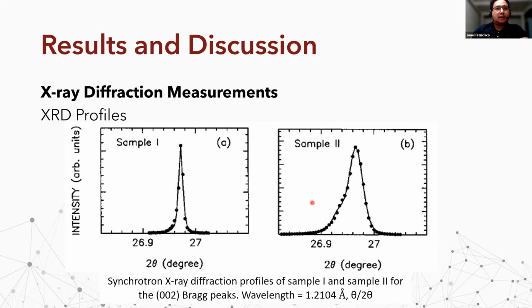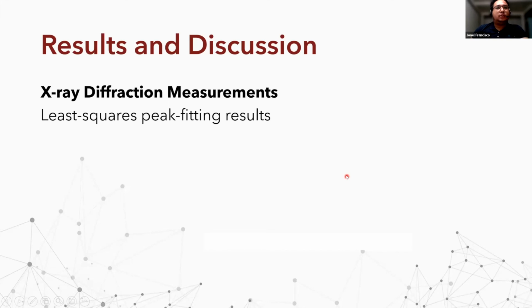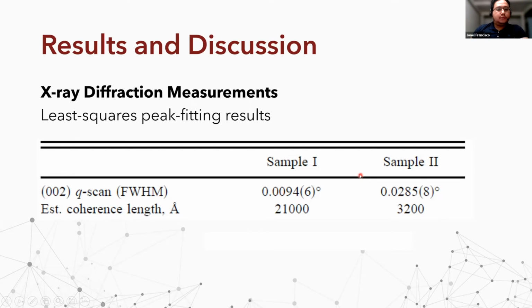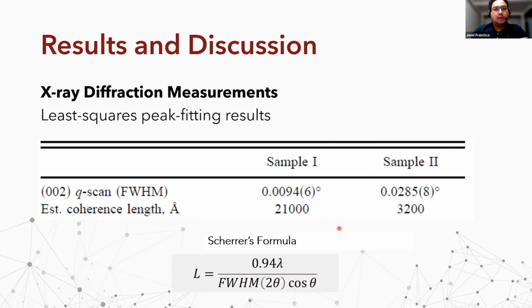The values were extracted from these profiles and placed in this table of least squares peak fitting results. The Q scan provides the full width at half maximum, which corresponds to the coherence length of the thin film. That is, it can be viewed as the crystallite size since we use Scherrer's formula to estimate its value. Sample 1 has a narrower peak width than that of sample 2, 0.0094 degrees versus 0.0285 degrees, while the coherence length of sample 1 is much greater than that of sample 2, with 21,000 angstrom versus 3,200 angstrom for sample 2.